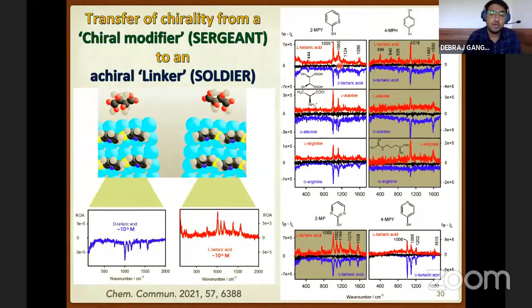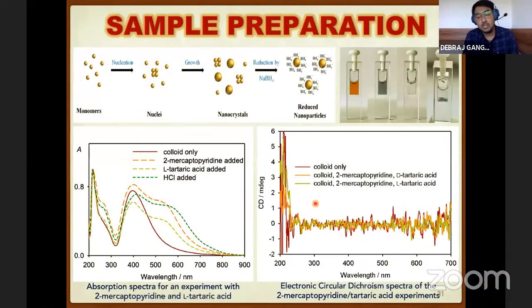It's in the range of 10⁻³, which is considerably high when we consider surface enhanced Raman optical activity. So these are reproducible surface enhanced Raman optical activity spectra, and we observe the surface enhanced Raman optical activity from an achiral molecule, which is also a remarkable thing. We observe Raman optical activity from achiral molecules due to surface induced chirality, which is induced by a chiral modifier. So how did we do it?